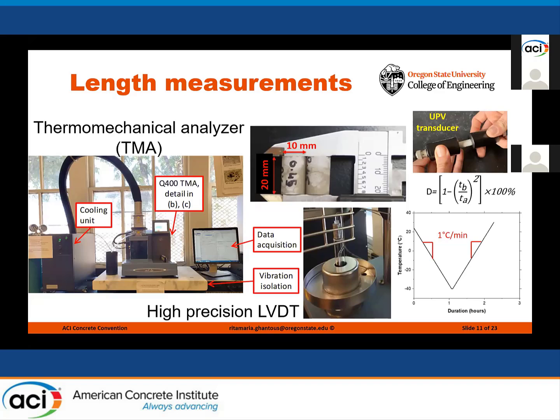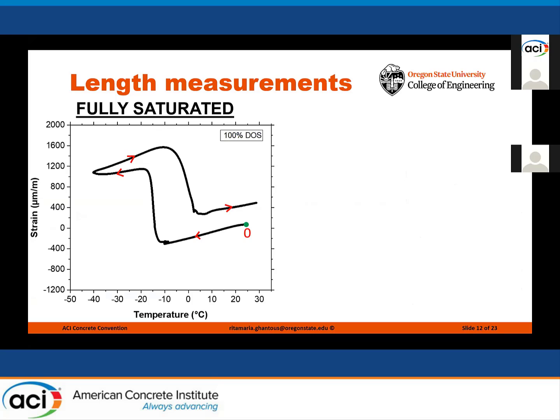So how do the results from the TMA look? If we look at a sample that's completely saturated, which is supposed to show damage because it has a DOS higher than a critical value, we can see the strain on the y-axis and the temperature on the x-axis. When the temperature drops, the length of the sample decreases until the freezing point where the ice starts forming. That's what we call the strain expansion, and it is determined by subtracting the strain at the end of the expansion from the strain measured at the beginning of the ice formation.